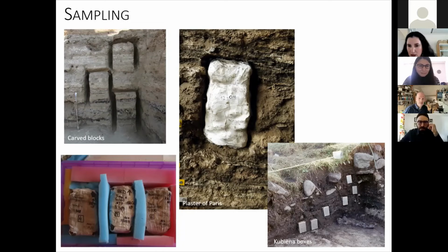Kubiena boxes, which are the ones in the bottom right image here, are also very widely used. They should always be gently pushed into the section or carved around, not hammered in, unless we're dealing with waterlogged deposits, because otherwise the sediment will get disturbed and it won't be that useful for micromorphology. These boxes, though, tend to be quite small, and they can be difficult to use in stony deposits, where you can't get a good fit, or you can have a stone sticking out from the edge of the box.